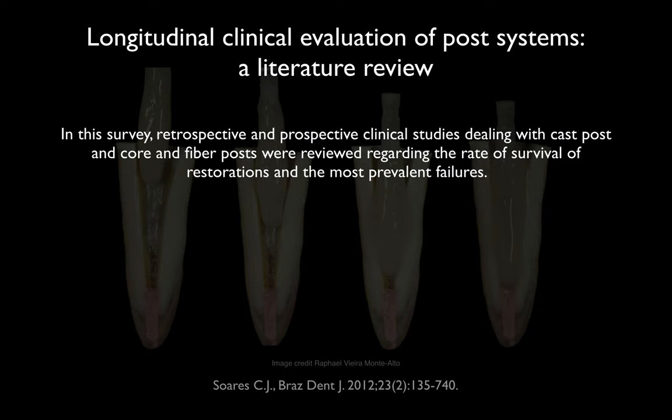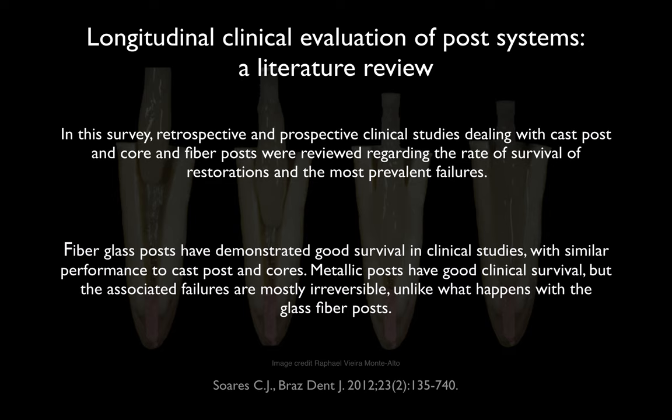Soares did a very good literature review of retrospective and prospective clinical studies, looking at cast posts and cores and fiber posts — examining survival rates and the most prevalent types of failures. He noted that glass posts demonstrated good survival in clinical studies, with similar performance to cast posts and cores. Metallic posts have good clinical survival, but the associated failures were mostly irreversible — meaning the tooth fractured — unlike what happens with fiber posts.